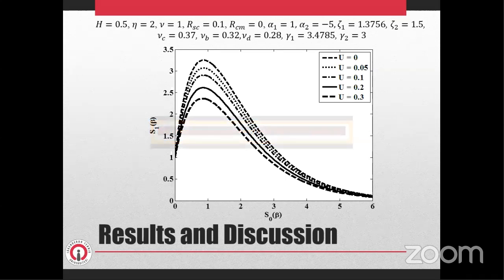This figure shows growth of the perturbation in solidified shell thickness as a function of mean shell thickness at selected values of coating thickness when system parameters are set as above. The result of the present model for U equal to 0 goes to the limiting solution in the previous work. As seen in the figure, the thicker coating decreases the amplitude of the growth perturbation at the solidification front. It can be seen that thicker coating layers lead to the faster decay of this perturbation, and it implies that the time for planar growth will be shorter when the coating becomes thicker.